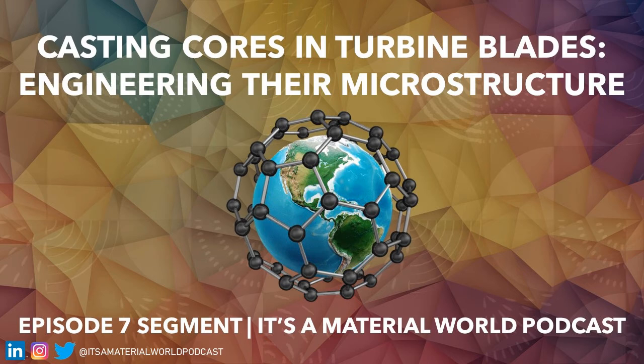And so it would be wonderful to have just an alumina core, aluminum oxide with no silica, because then you would minimize the reaction between the silica and the metal. However, the more alumina you have in the core, the stronger it is. And as I mentioned earlier, you don't want it to be too strong. And so that's where the Goldilocks comes in, right? It's got to be just right. And so there is a lot of development in mullite cores, which is an aluminosilicate, to basically be a less reactive core material. So there's actually a lot of science that goes into making these cores in terms of the microstructure and the composition because of the reactivity with the metal.